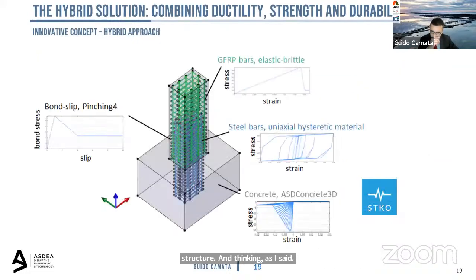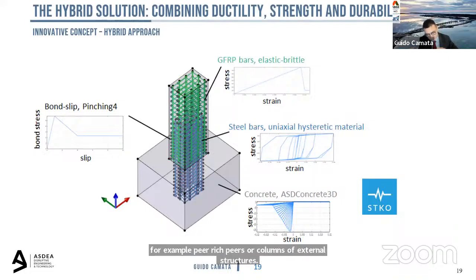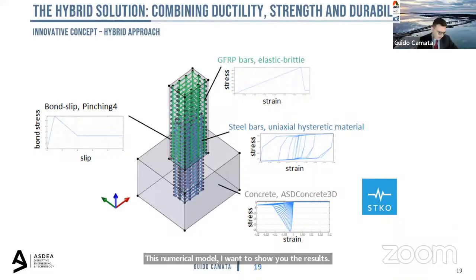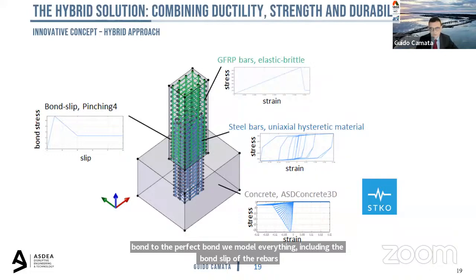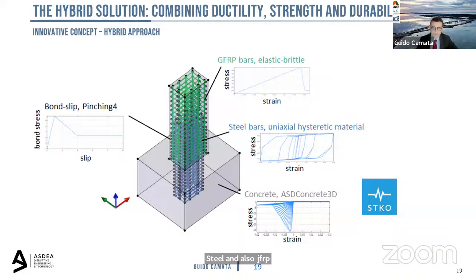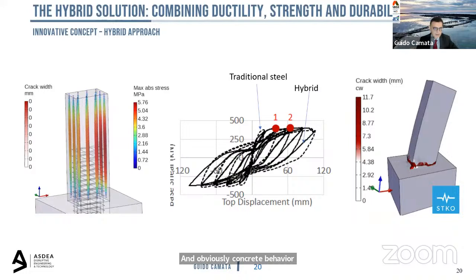So this is a numerical model. I want to show you the results. So here you can see the internal cage fully anchored to the foundation, and the external cage GFRP not anchored. So we are not even concerned about the bond of this kind of rebars because we don't need to guarantee the perfect bond. We model everything, including the bond slip of the rebars, steel, and also GFRP, and obviously concrete behavior and GFRP elastic brittle behavior. Look at the results.